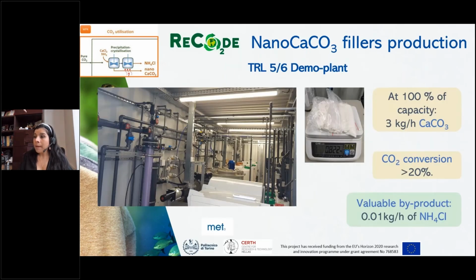Finally, here you see the plant that is installed at Titan facilities that was constructed by MET. Here our goal is to have, at 100% of capacity, a final productivity of 3 kilograms per hour of calcium carbonate with a CO2 conversion higher than 20%, and the possibility to produce additionally another valuable product that is ammonium chloride.